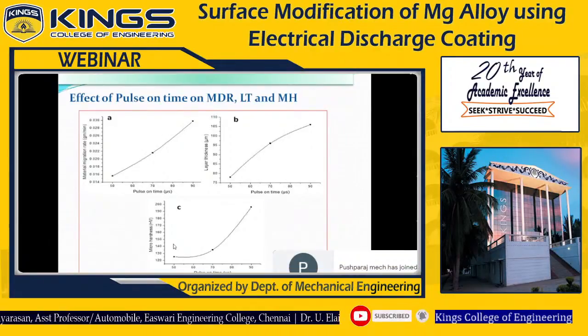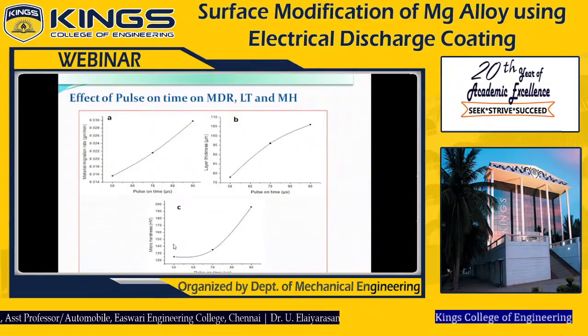Here also, at the lowest pulse on time, material deposition rate is very low, because at low pulse on time, the diameter of the produced plasma channel will be very small. Plasma channel means the size of the flame. Very small, which is not sufficient, which produces the discharge energy and discharge intensity, so spark density. These are the producers. Based on those mechanisms, the electrode has been melted.